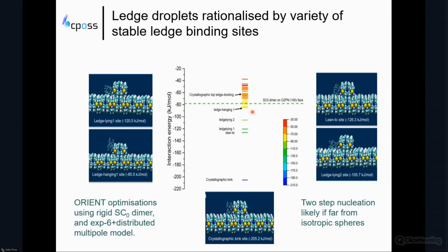And this aspect of having a two-step nucleation, where your molecules get together and densify as one step, and then the nucleation takes place, you can see is likely to be very common when your molecules are far from spherical and are not, as you do in classical nucleation theory, going straight into the crystallographic site on the nucleus.